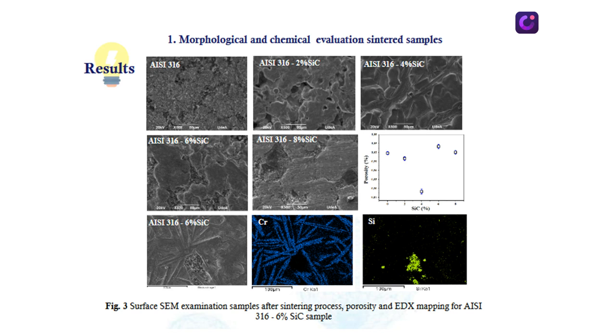On the other hand, the sample with 4% reinforcement showed a compact microstructure after the sintering process with a good compatibilization at the interface of the matrix and the reinforcement. The samples with 6 and 8% show areas where the reinforcement is not homogeneously distributed and the matrix is present on the surface of the materials, showing that the reinforcement was not compatible with the matrix at the interface. During the evaluation of the porosity, the 4% silicon carbide sample showed the lowest value, even lower than the steel. On the other hand, the 6% reinforcement showed the highest values, surpassing the steel.